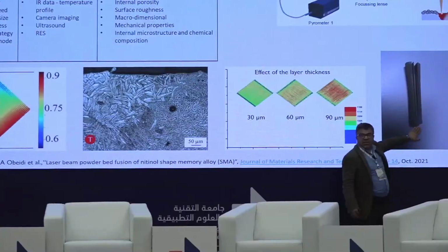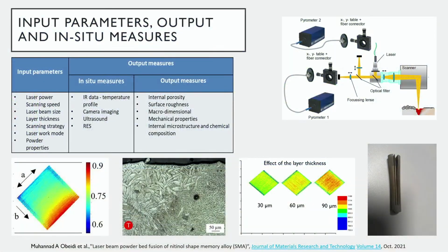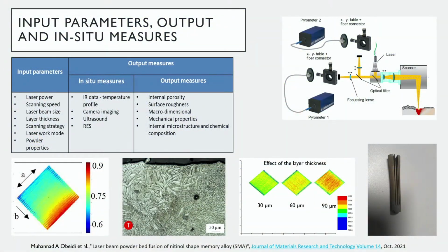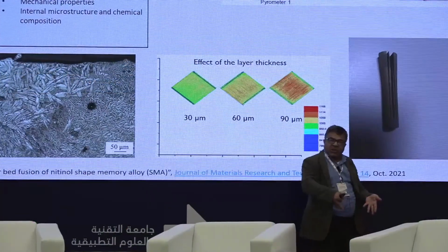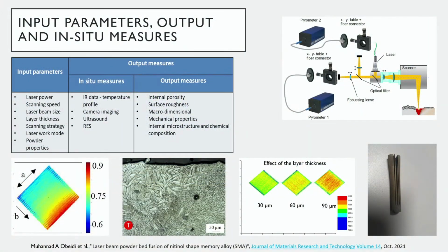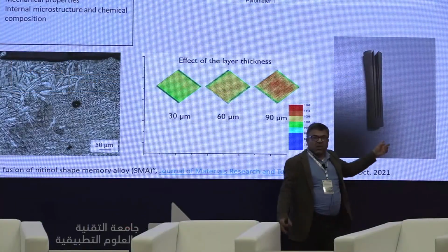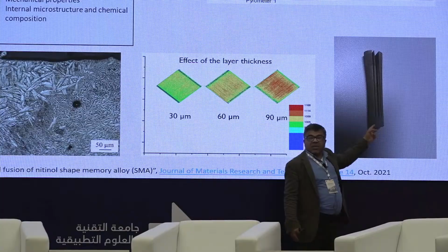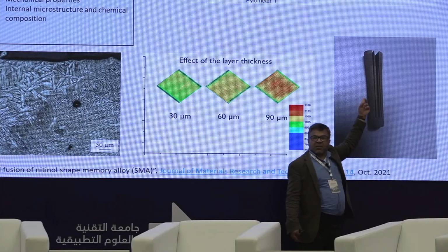The other drawback actually is the non-isotropic behavior, as Dr. Saad mentioned yesterday. The process is not isotropic. This pin here, for example, was printed in this direction, bottom to top. When we start printing, it's room temperature on the build plate and the powder. As we proceed with printing, with every layer, we are adding more thermal energy. So the top has larger grain size in the microstructure compared to the bottom. The bottom is higher strength than the top.